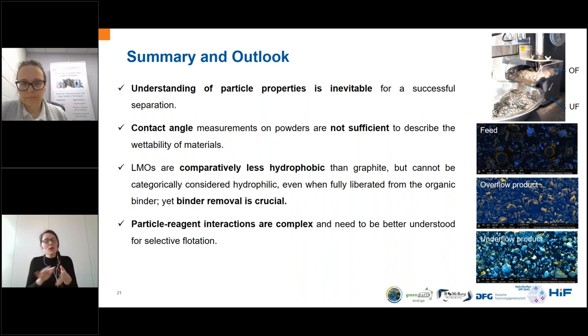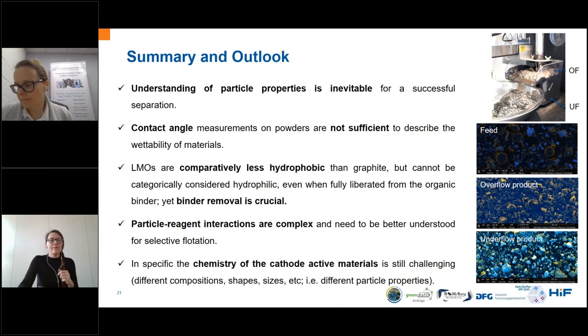So for flotation, I only showed you one reagent, but usually in flotation you have a frother, you have a collector, which renders the particles hydrophobic. You also have depressants, which render other particles hydrophilic. So you have a lot of chemicals and reagents in there, and a lot of interactions, which are really complex. You also have the hydrodynamics. You have a suspension phase. You have a froth phase. So it's really a complex process, and there's a lot of research going on in that field.